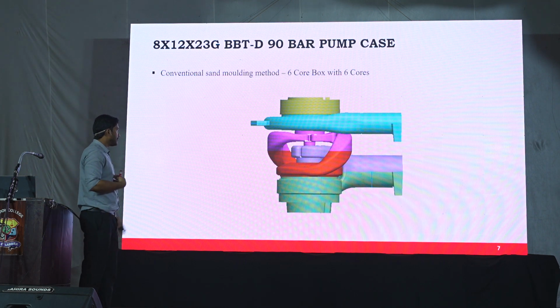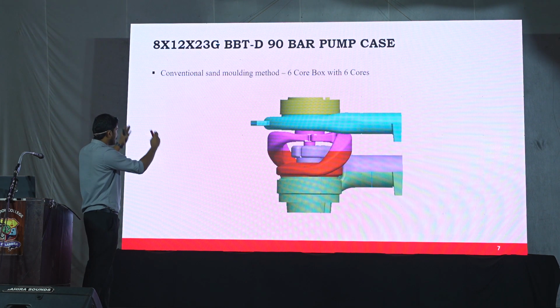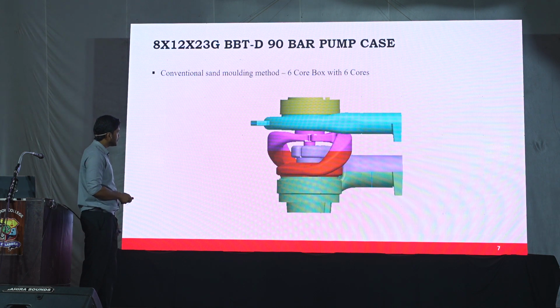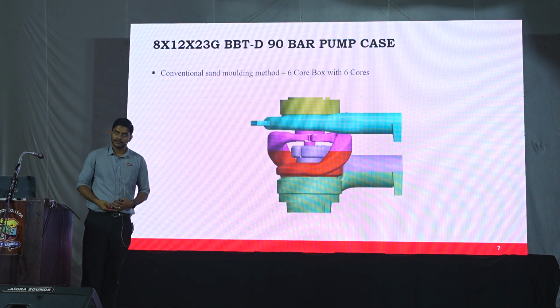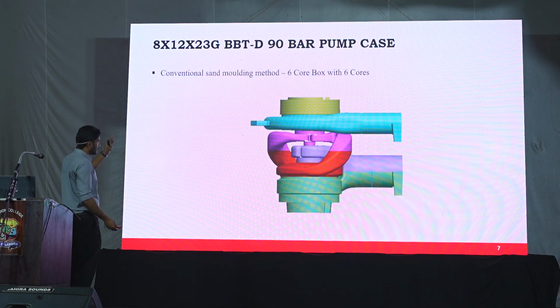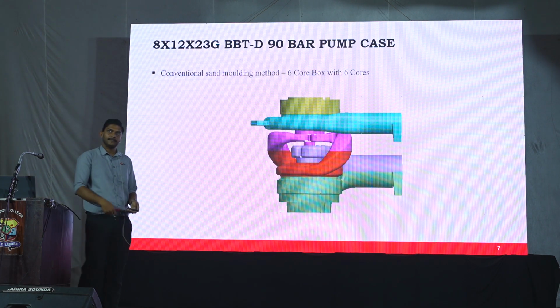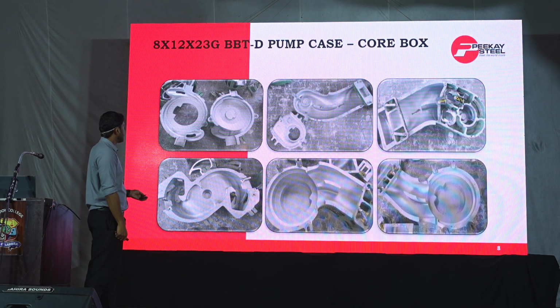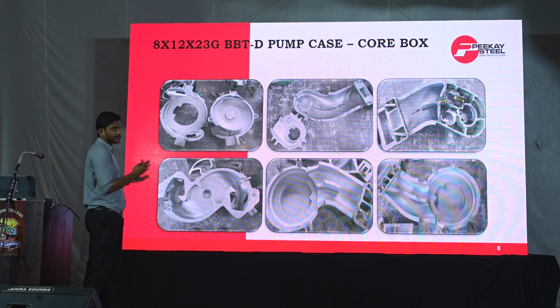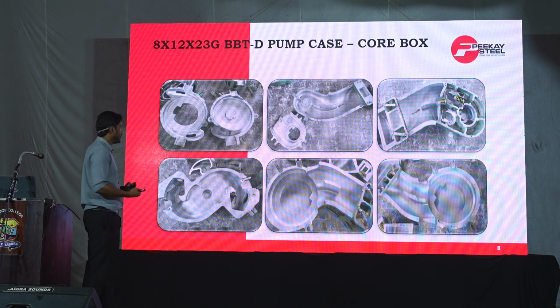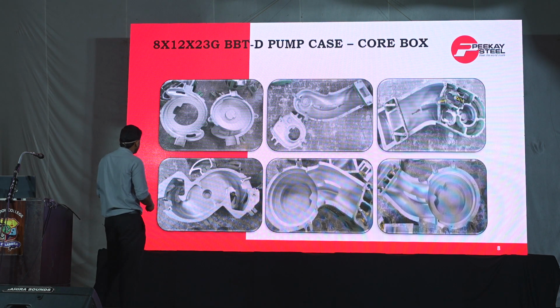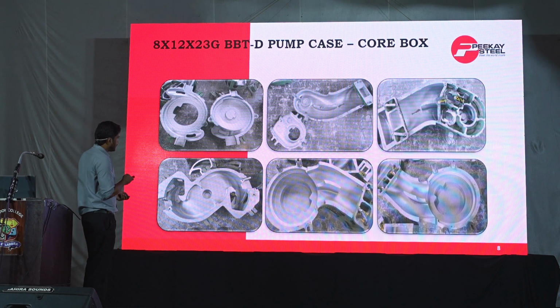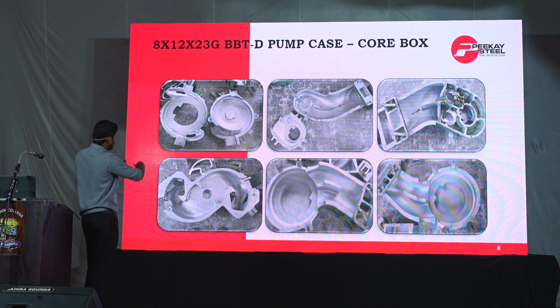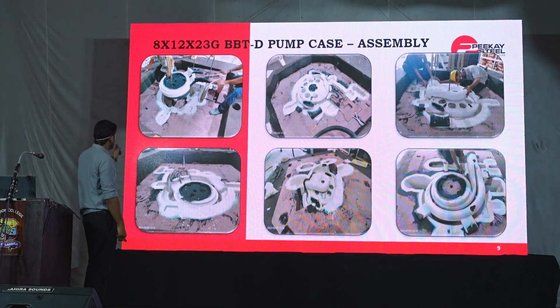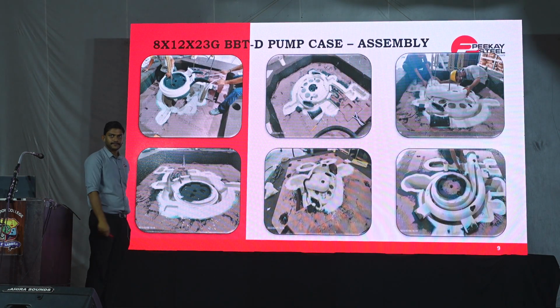And since we are making it by hand, we cannot make it all in one stretch. So the different colors indicate different pieces. You can see there are 6 different pieces here. We make this through the alkaline phenolic process and bind it. For making 6 pieces, we are making several boxes which are made either of aluminum or of wood. And with all this tedious work, we bind with the binder, resin, and hardener, mixing the sand into it, molding it, making the cores like this, and we assemble it.